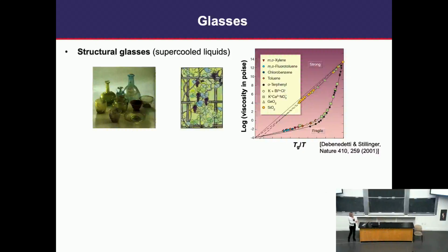This figure here shows that as we cool them down quickly, it's more difficult for them to move, to flow. The viscosity grows, and here we have a figure for several different glass-forming liquids where viscosity is shown on a log scale. You can see as you reduce the temperature, the viscosity increases by 14 or 15 orders of magnitude.